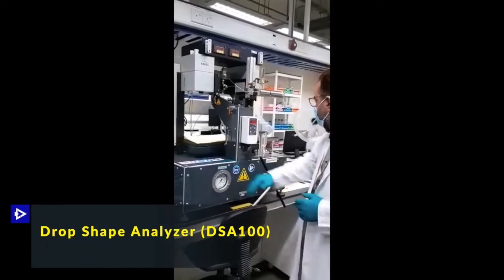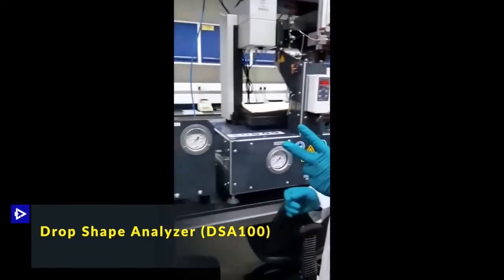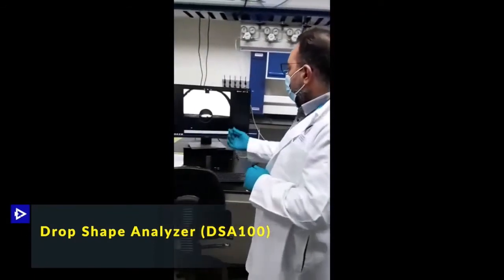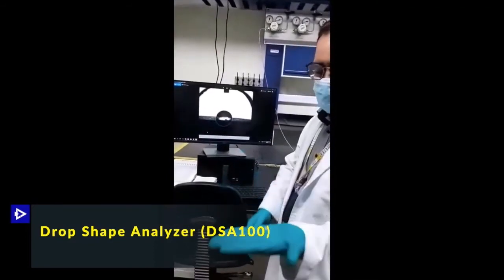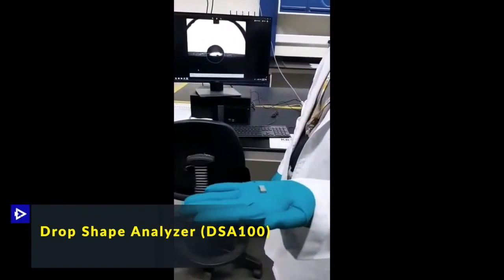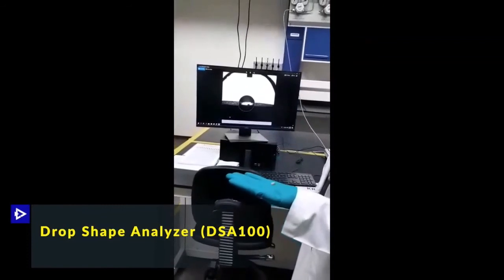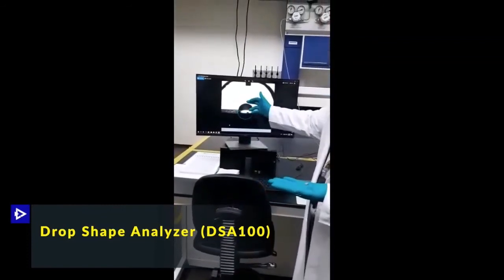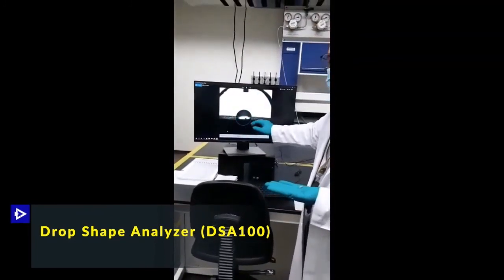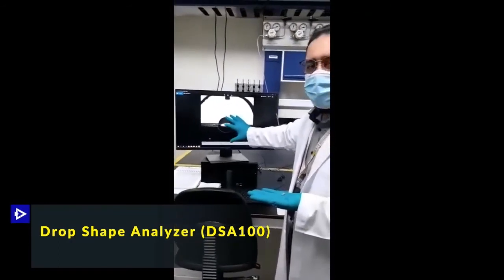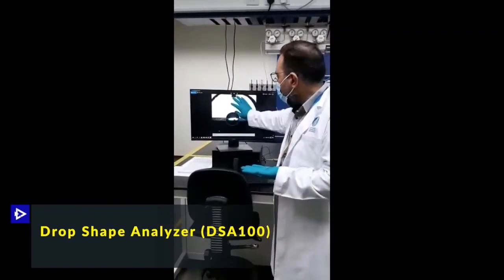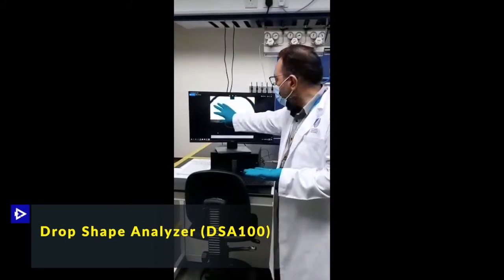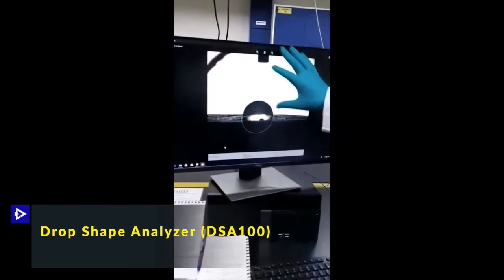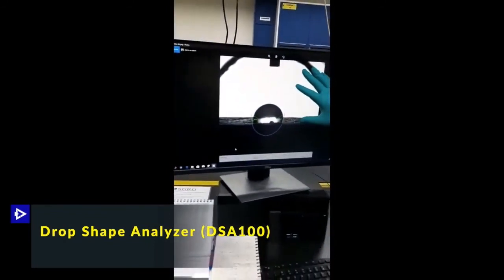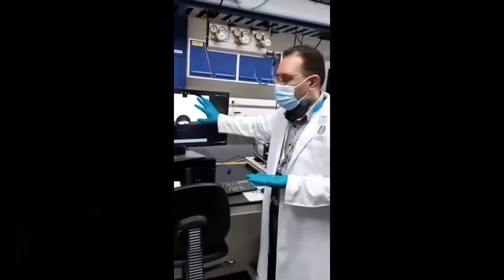In this equipment, we have some types of shale material that we can study with 2 types of measurements, whether studying the contact angle and wettability of the shale. This is the type of shale that we need to utilize, which needs to be polished with a very flat surface. Then we can drop fracking fluids, or even crude oil, or any type of emulsion that we are mimicking or predicting, depending on the reservoir conditions and the reservoir environment, which can be any kind of gas, such as CO2, methane, nitrogen, helium, or even some liquid hydrocarbons.